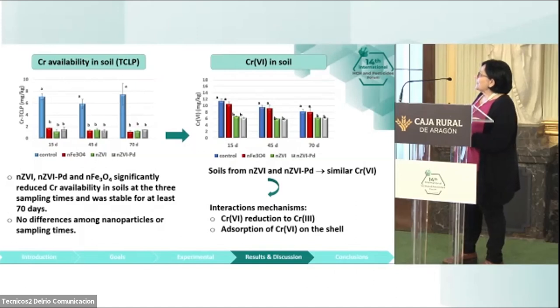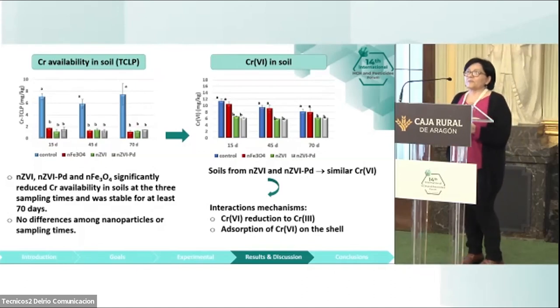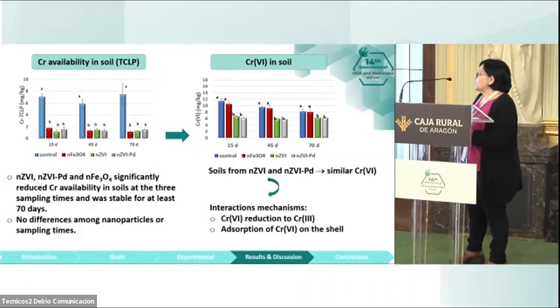If we analyze the remaining chromium in soil, we can see that the treatments with nano zero-valent iron, both with palladium and without palladium, had the best results in comparison with the nanomagnetite. There were similar concentrations of chromium, and the mechanisms that can be involved are reduction, because we are talking about chromium: chromium 6 is reduced to chromium 3. And we can also have an adsorption of chromium 3 or 6 on the surface.